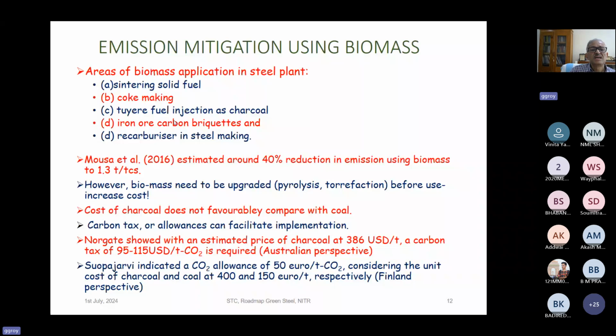Then iron ore carbon composite briquettes we can use in the rotary hearth furnace. In the rotary hearth furnace, there is scope for using biomass as a carbonaceous source during briquetting, because those briquettes do not require sufficient strength. So those briquettes can easily be charged into the rotary hearth furnace and converted to sponge iron for subsequent melting, either in the blast furnace or in the electric furnace. And the biomass also can be used as a recarburiser in steel making. It can be charged as a recarburiser, that is, if you want to increase the carbon in the process.